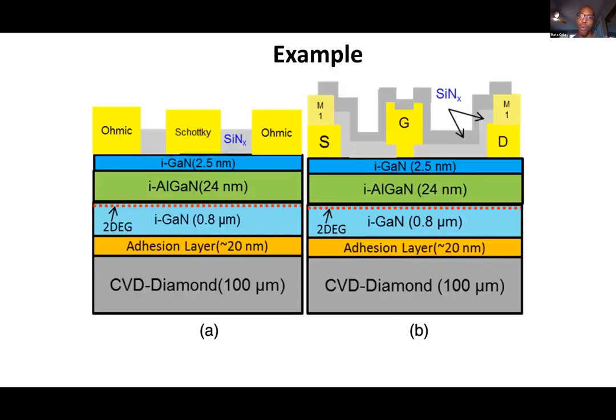Here's an example of things that researchers have been looking at for some time now to be able to put heat spreading close to the hotspots. So here you have a GaN device. Diamond, which is a known very high thermal conductivity material, is grown on the backside or it's adhered. But this highlights these issues and these challenges that we have in terms of diamond may have a very high conductivity, but you have to have an adhesion layer or there's an interface and it will dictate its ability to spread effectively. And so these are the opportunities that we have in both thermal interfacing and heat spreading.